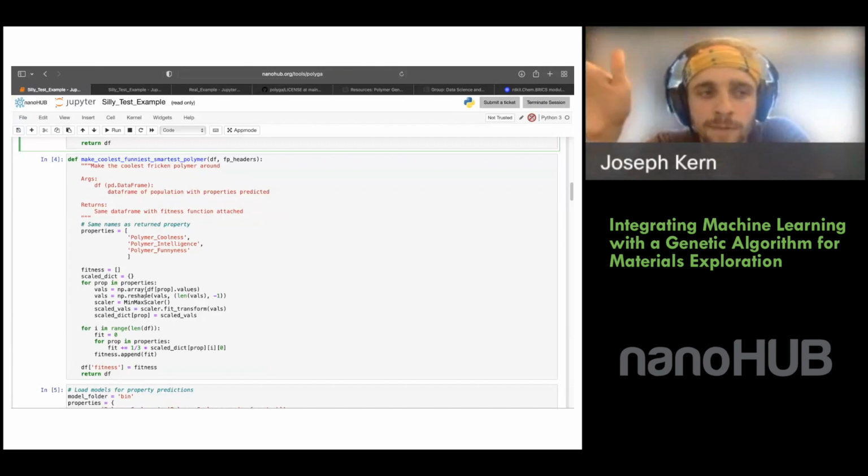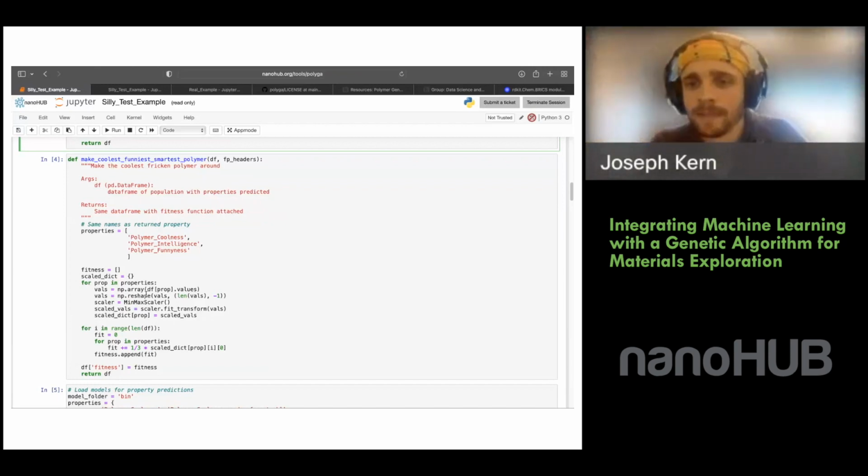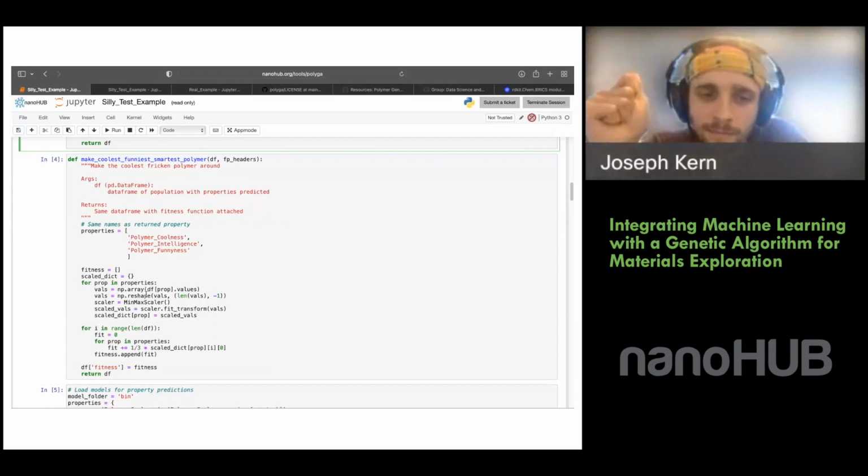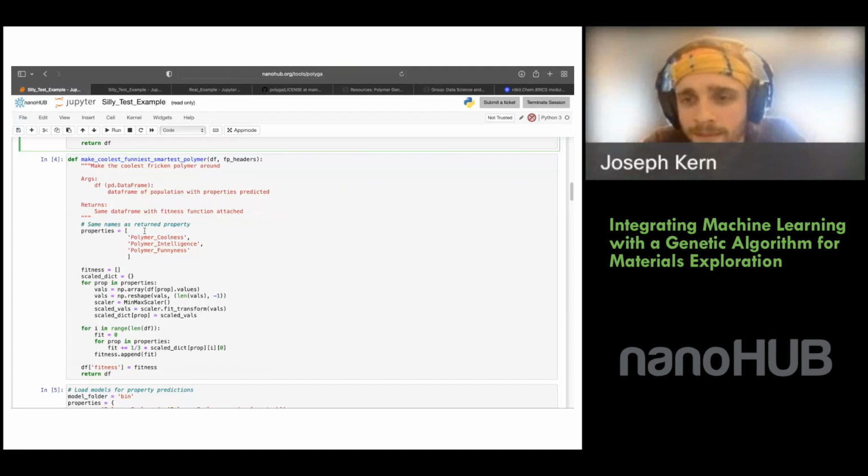I found that what works better is trying to figure out what mutation rate corresponds to a stable length. You don't want to constrain the minimum, because sometimes these 2-block polymers are very easy. They're much more likely to be synthesizable. So if you say you can only be 4, then that's not good. But you can constrain the max length. You could absolutely add that in the fitness function if you wanted to. I've done that, and it does work sometimes. It does make more realistic polymers.